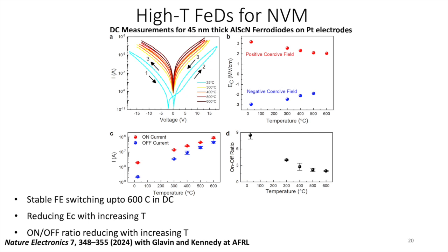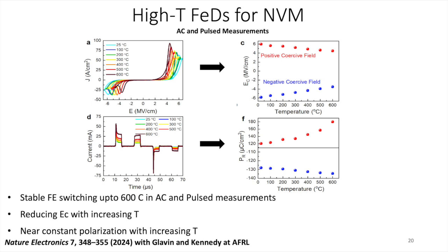One of the hallmarks of computing is fast operation. AC and pulse measurements are also necessary. So if you go to the next slide, which is slide 19, there we have shown the same thing working in AC measurements at 10 kilohertz, and then also pulsed measurements with 500 nanosecond pulses. You can see very sharp and clear switching of ferroelectricity up to 600 degrees Celsius. Once again, you can extract material parameters such as coercive fields or remnant polarization from these measurements.